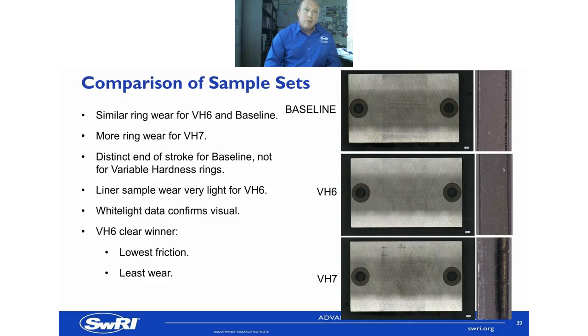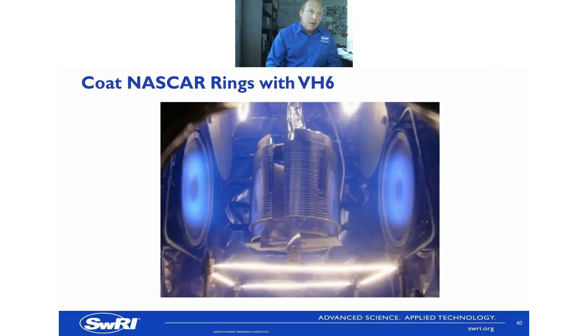All 3 there just for comparison, so you can look at those together. There's more ring wear for VH7, similar ring wear for VH6 and the baseline. You can see the distinct ends of stroke on some of them, but not on the others. White light data I've not presented, that can be a bit confusing, but that confirms the same as the visual that we're seeing here. So VH6 is a clear winner. It's the lowest friction and the lowest wear. So let's take that and coat it.